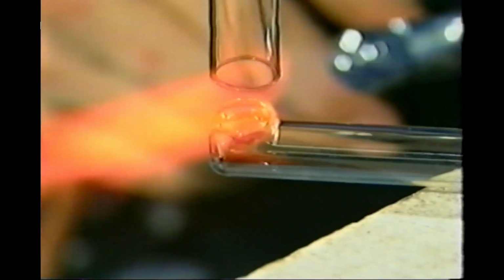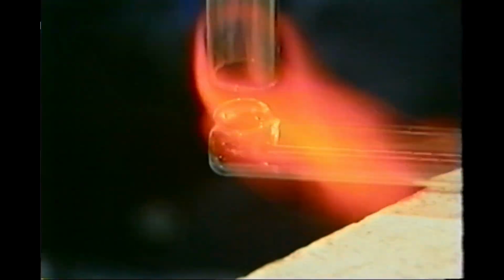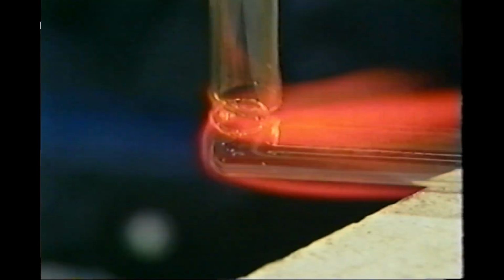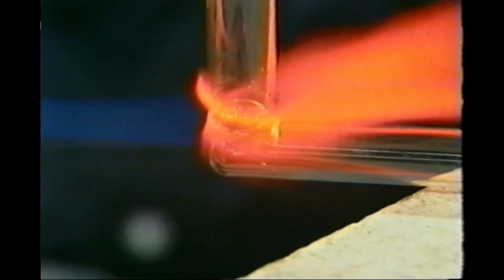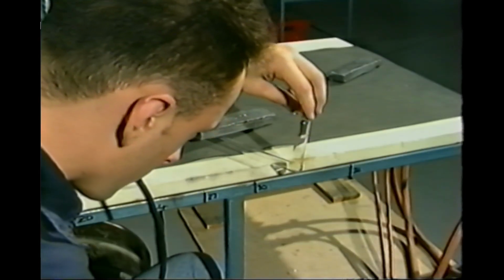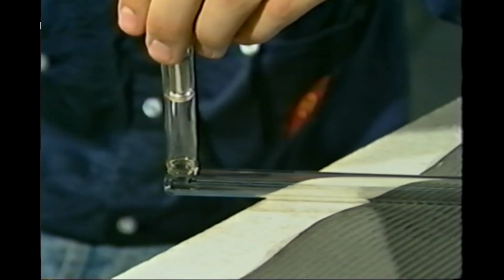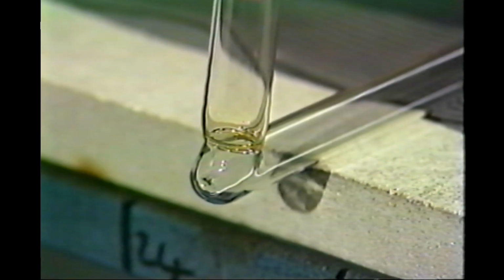Melt evenly both parts with complete rotations of the flame. When both parts are correctly molten, remove the flame, touch gently the open end of the electrode to the edges of the hole, give a slight blow, and pull upwards gently. This blow and pull will thin out some of the ridges and folds formed by the initial contact.